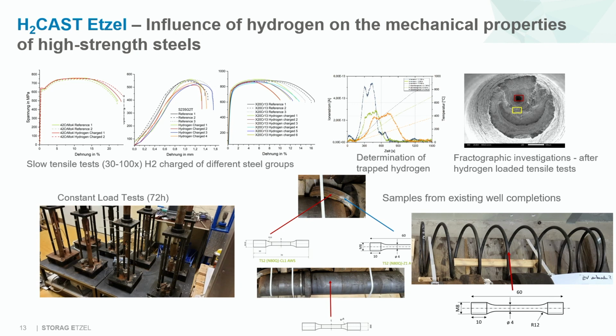For example, we tested existing wells' typical materials under a hydrogen atmosphere. We tested the hanger of the cavern, the part where the maximum load is in the cavern completion. And maybe anybody knows what this is here. It's a spring, and this is very important. It's a spring from a subsurface safety valve. I think it had never been tested before, because we dismantled one of the safety valves and put all the pieces into the laboratory and tested them with hydrogen, because the supplier of the materials can't give us any guarantee that it will work. Then we thought, when we come to the conclusion, we have to do it ourselves, to test it, to go forward with it.